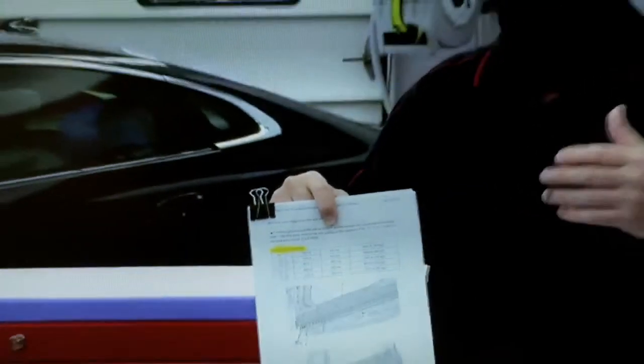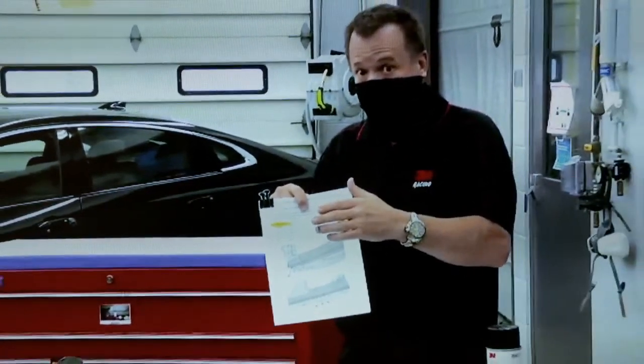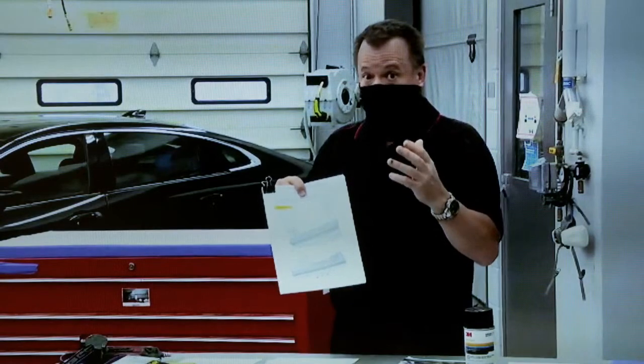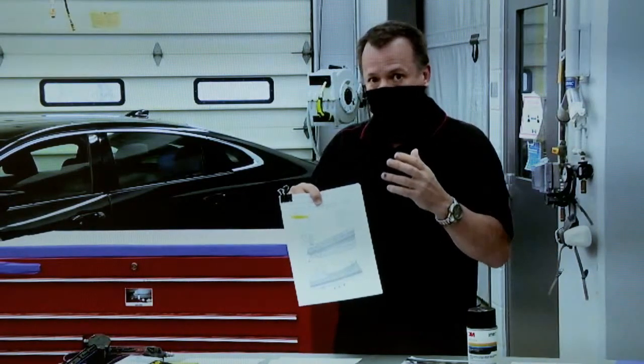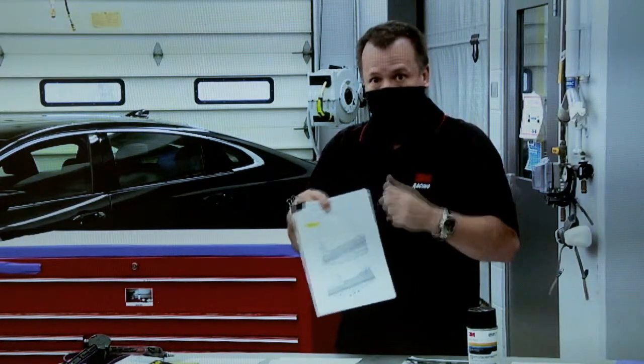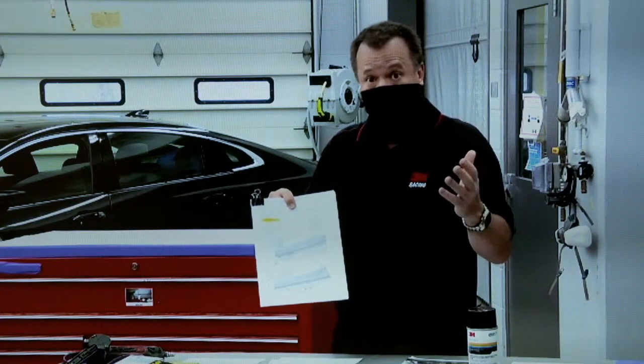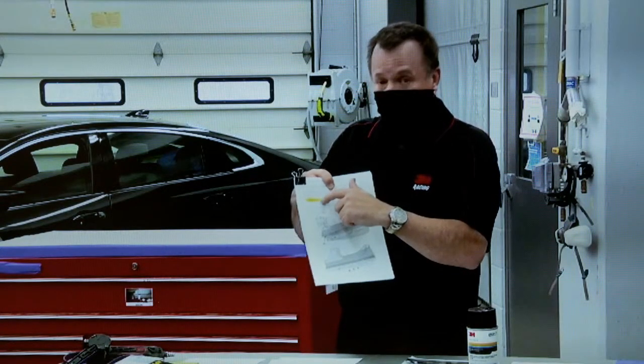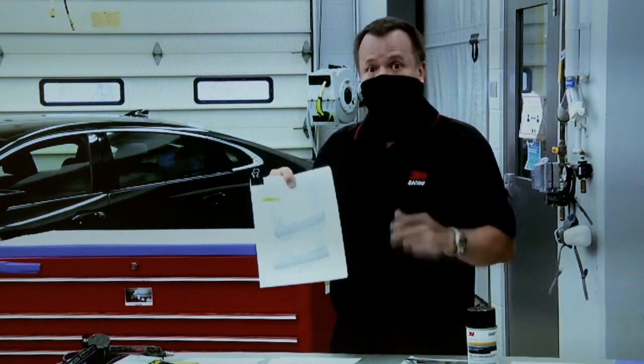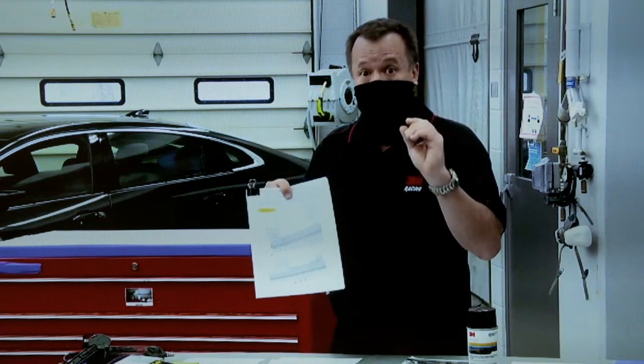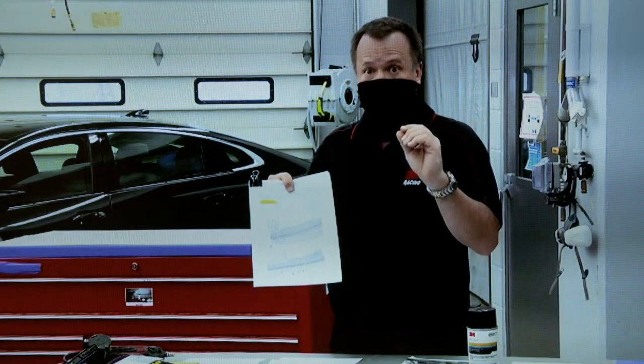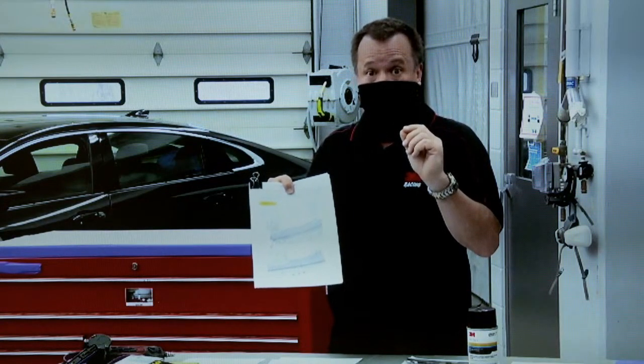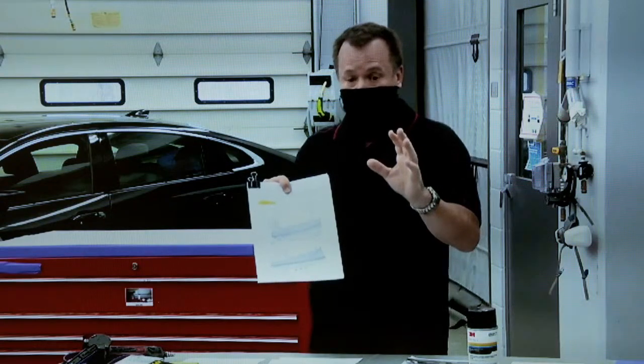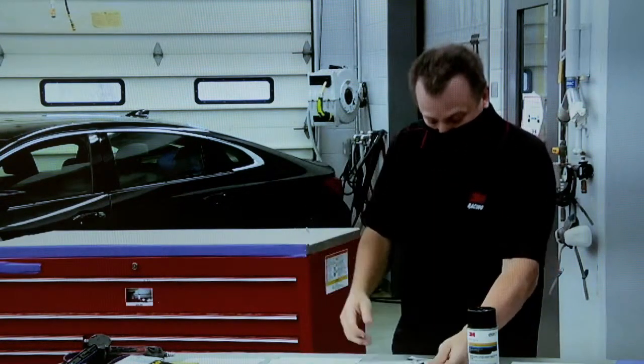I tried it both ways. One time I was working on a prop, and I tried to weld on automatic. I found out you could see that it was welding it, but just barely. If you twisted it or pulled it apart hard, it came apart. That's how bad it was. Then when I turned the machine to the manual settings, you could notice a noticeably longer hold time, a much longer time to hold it and make a longer weld that's much hotter. So be very careful about that, and that's why Honda has that information.